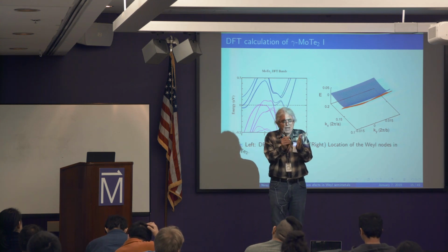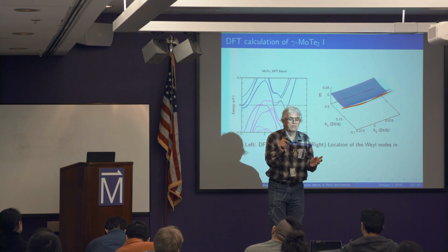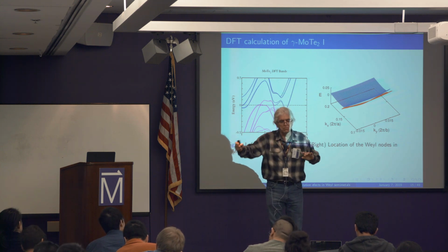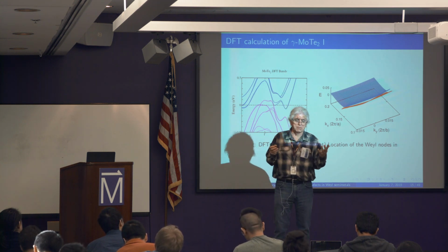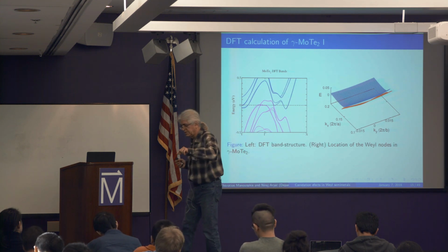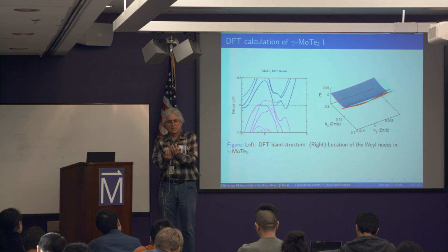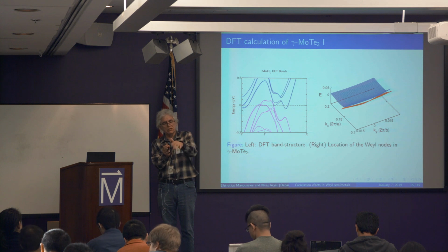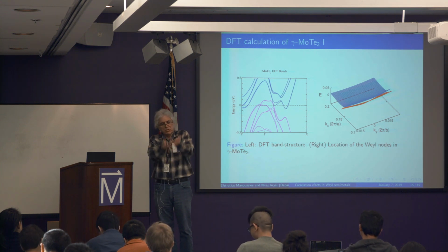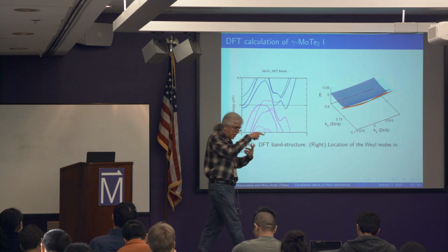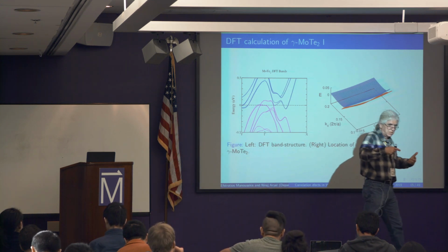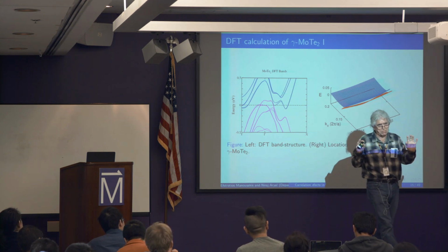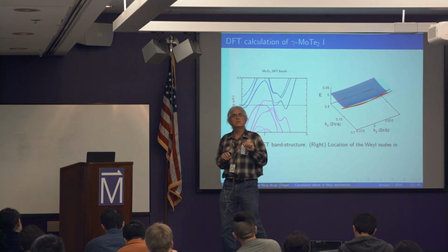What counts is the effective repulsion from the other electrons that occasionally visit that orbital, when an electron jumps to a d band. So you have electrons swimming from one orbital to the other, if you like, in a semi-classical picture, and from time to time they hop to a d site. But the d site is a small room, and you're trying to double-occupy a very small room in a hotel. So your energy will go up, compared to going to a room in a hotel where there's another occupant but it's a huge room. You can spread your legs and everything. No Coulomb repulsion there. So this is the effect we are talking about.